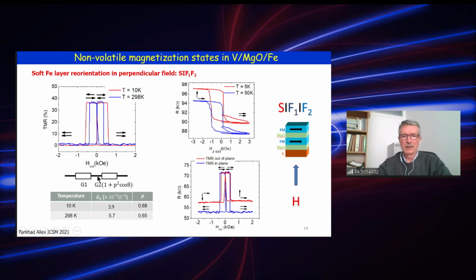From these different magnetic resistances—in plane, out of plane, perpendicular—we can extract spin polarization. Effective spin polarization of iron here is around 0.7.